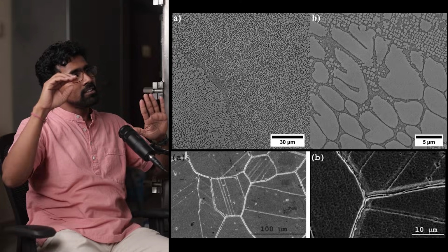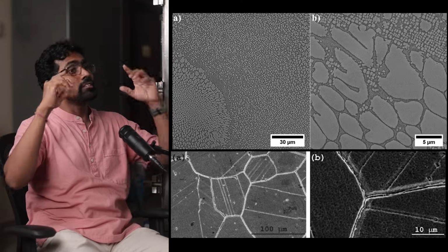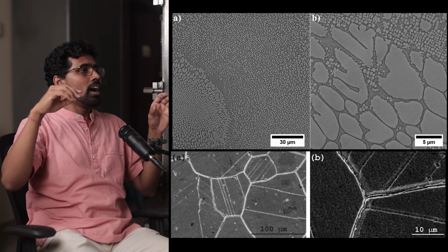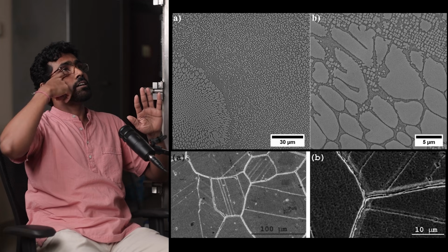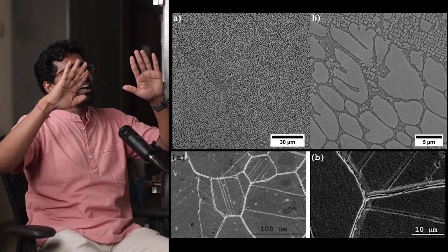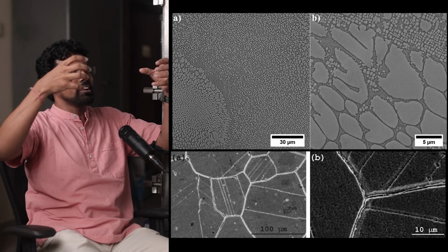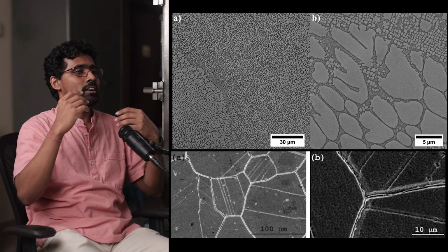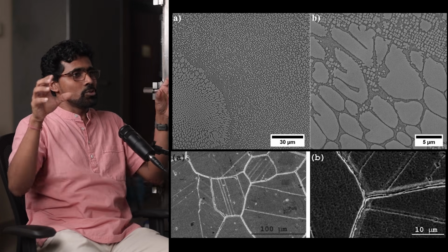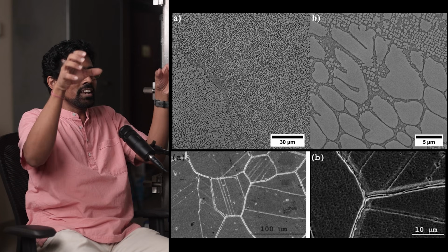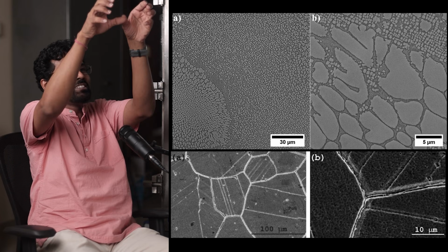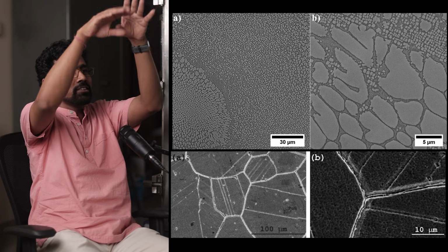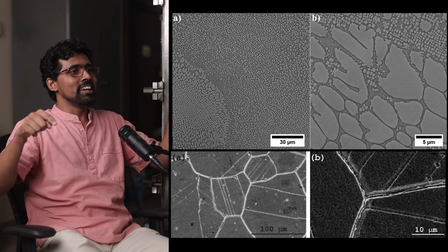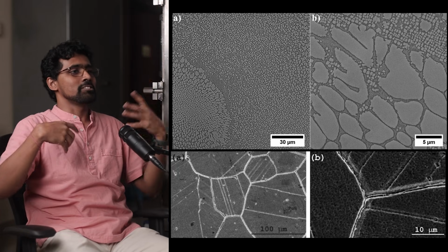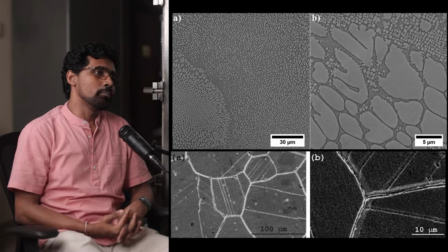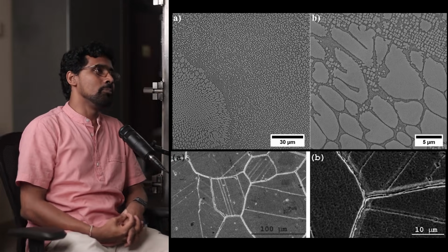So let's say these are growing on the atomic scale. You have a crystal growing in this direction, and there is another crystal. Consider it as a cube, because in nickel superalloy it's a cubic structure. So you have 2 cubes which are growing like this, and then they come and meet somewhere. Then they can't grow anymore, it's already solidified. And those form the grain boundaries. That's how solidification happens and the grain boundaries form.